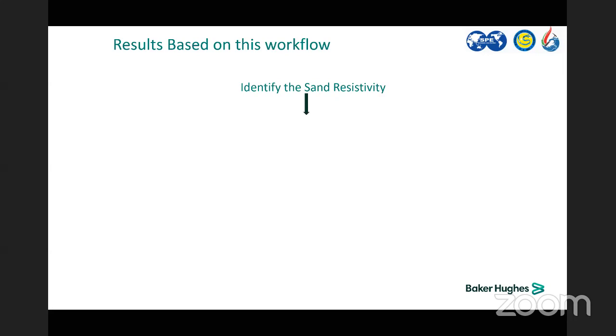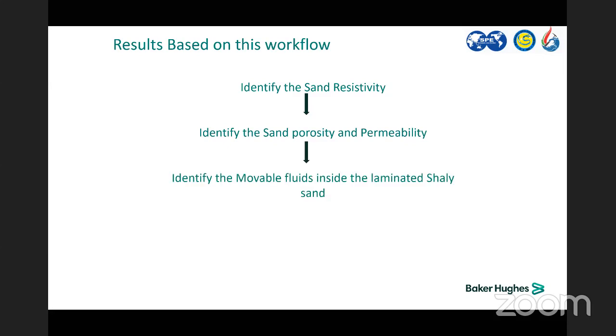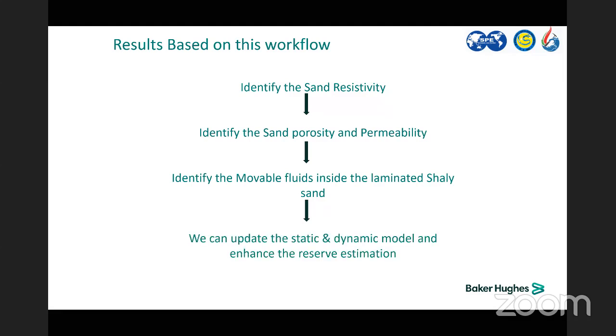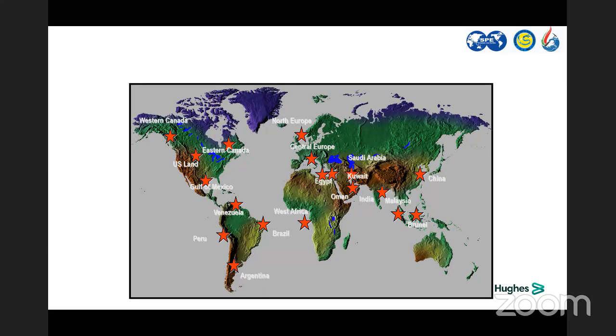So the result based on this workflow is to identify the sand resistivity and the sand porosity and permeability with a true resolution, and identify the movable fluid. Once we identify the movable fluids and the true porosity and true permeability and true sand resistivity, we are able to update the static and dynamic model and enhance your reserve calculation, and there are no bypassed hydrocarbon in the thin laminated reservoir.